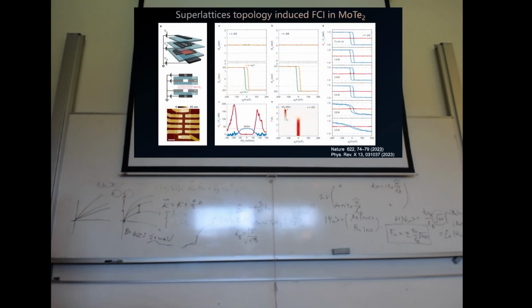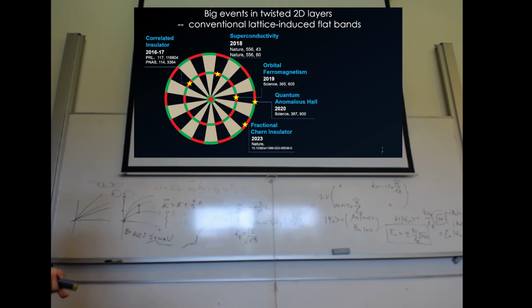And this is the one I just mentioned. So in 2023, two papers came out almost at the same time, from two groups. One is from Shanghai Jiao Tong University, the other is from Washington University. They studied the same system with a tiny difference in the contact method. But in the end, they reported the same result: if you twist this MoTe2 by an angle of 3 point some degrees, you will have integer and fractional quantized plateaus at zero magnetic field, and the phenomenon is very beautiful. So that's how it was evolving in this system.